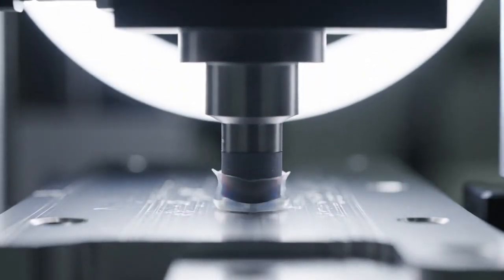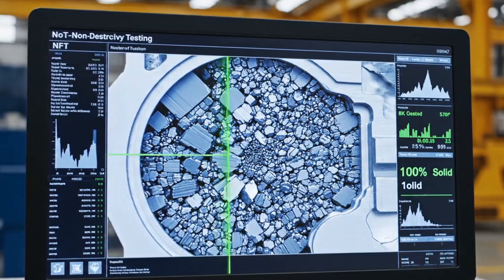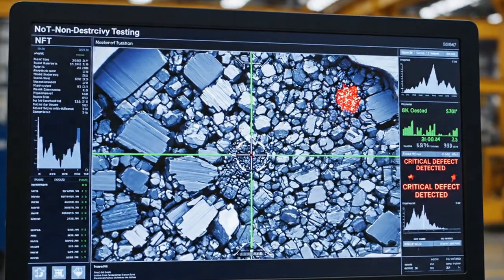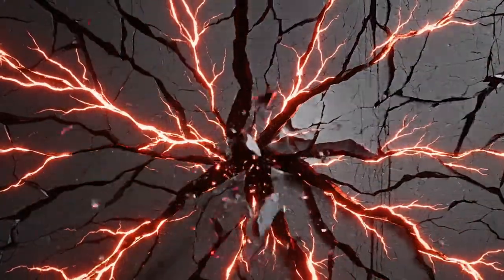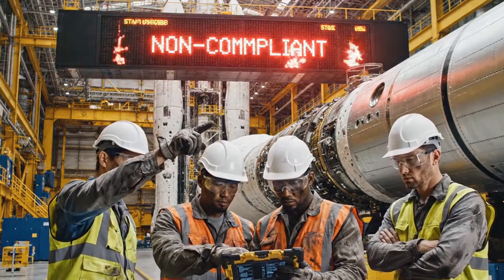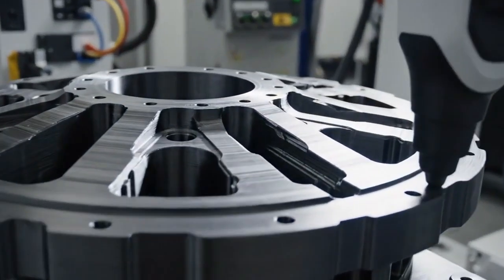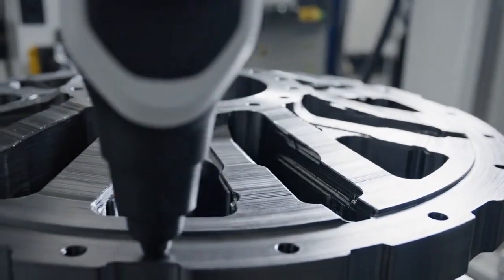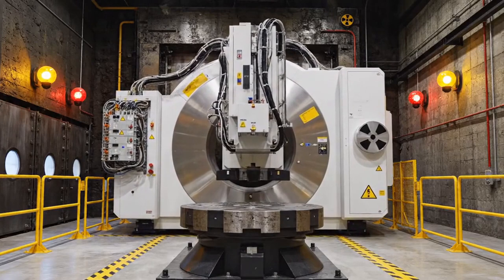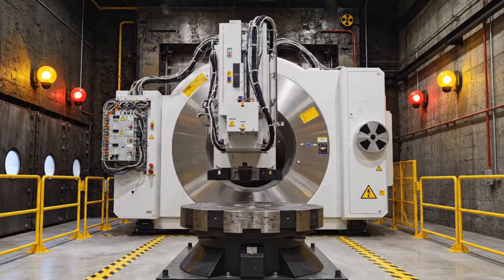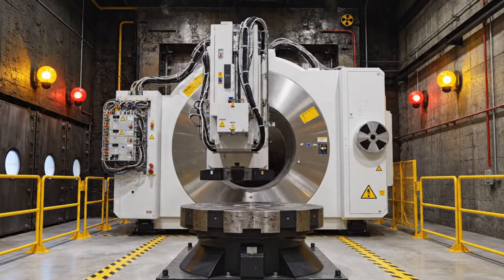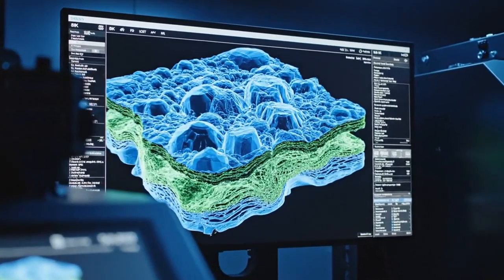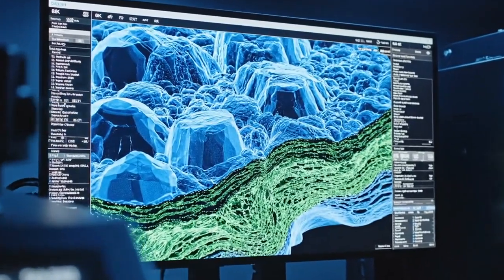The tolerance threshold is exceptionally strict. The system is calibrated to identify microporosities or lack-of-fusion defects with a diameter smaller than 0.1 millimeters. Any volumetric void exceeding this microscopic parameter could propagate into a critical fracture under launch conditions, rendering the stage non-compliant for flight. For the thickest structural sections, such as the engine mounting thrust puck, industrial computed tomography, or CT scanning, utilizing linear accelerators generating mega-electron volt X-rays, provides a complete three-dimensional volumetric reconstruction of the internal grain structure.